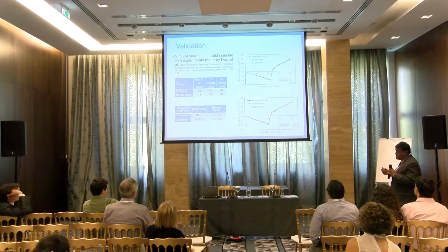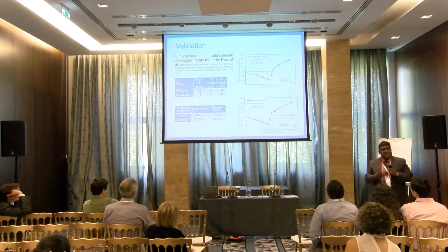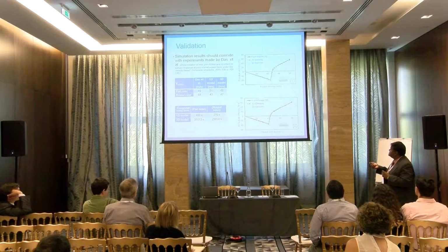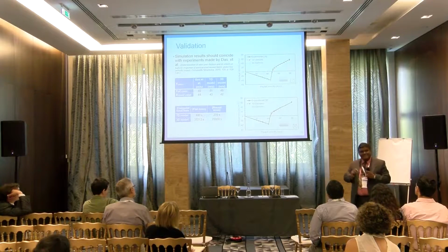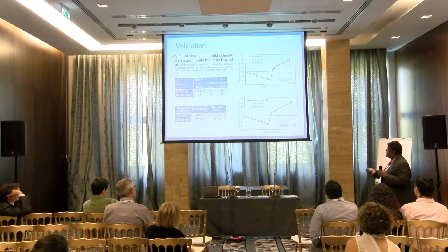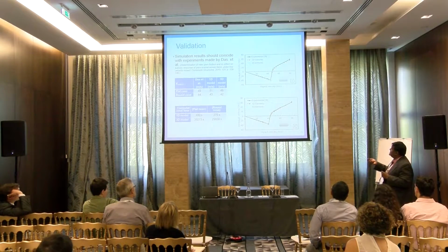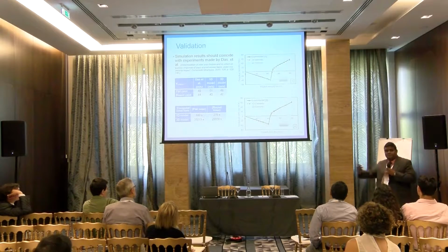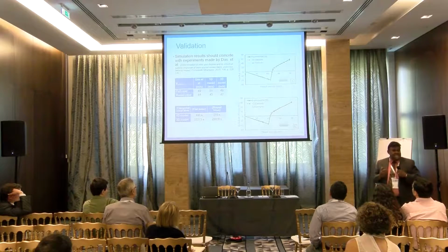So what we found here, let's look at this diagram, is what really happens at different impact velocities. When the impact velocity is low, the projectile is rebounded. But that rebound doesn't happen with the same velocity. It is not a conservation law, because for a fabric there will inevitably be damage. If we simplify the case in physics, we have an inelastic collision, so there will be energy dissipation. As a result, when the projectile rebounds, the residual velocity is negative, opposite to the direction of the initial velocity. This line is not 45 degrees, it is less than 45, showing the residual velocity is less than the initial velocity.